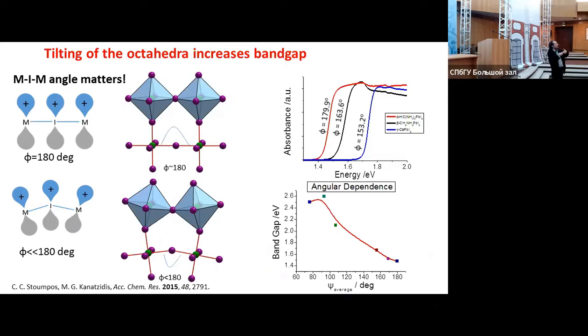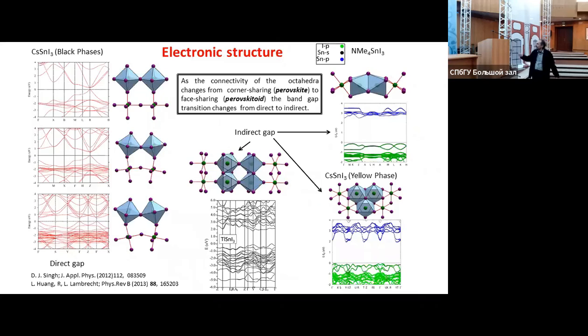If you tilt too much, you have another change in the optical absorption. So the optical absorption essentially depends on the angle of the tilting for a given set of compounds, in this instance, lead iodides. And we're in this region here. If we go to the other structures, you see the non-perovskitic band structure. You get much larger band gaps with much less interesting electronic structure, like the ones that you will see here. And these are the perovskite band structures as you go from the cubic, tetragonal, and orthorhombic phases.